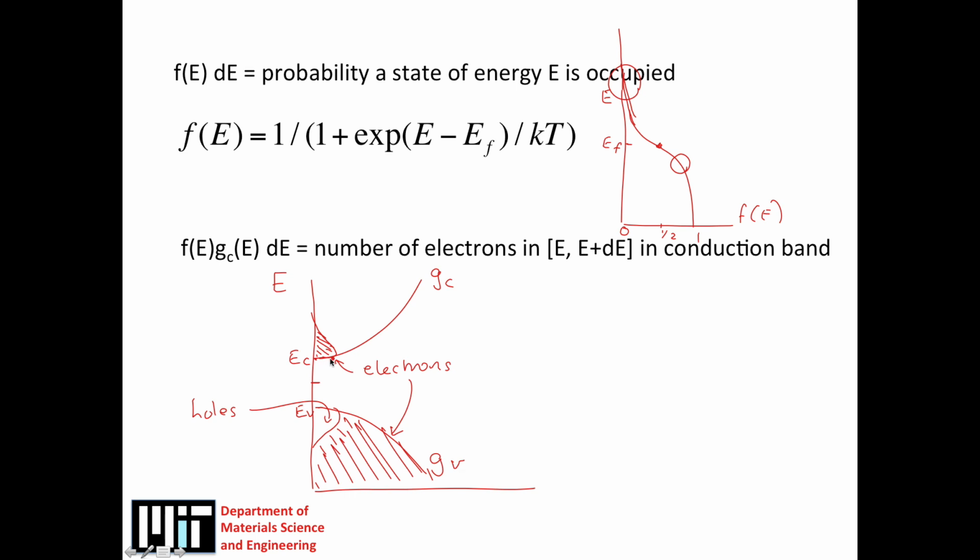So we get a point here which is on the order of kT above the conduction band edge, where we have the maximum density of carriers, and as we go above that we can see this exponential decay which is coming from the tail of this Fermi function. And similarly, the holes are mostly around kT below the valence band edge, and as we go down in energy, the chance of finding holes with these very low energies gets smaller and smaller exponentially.